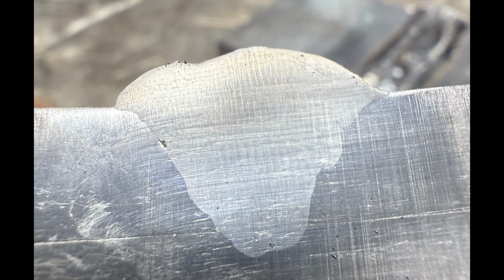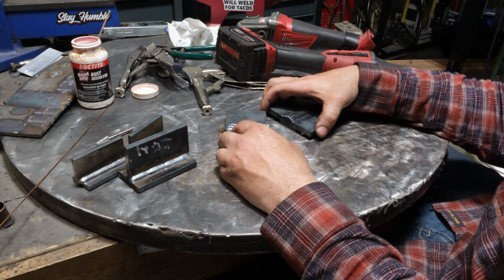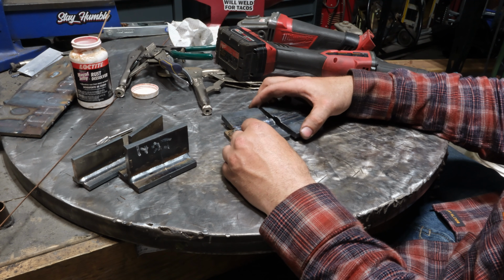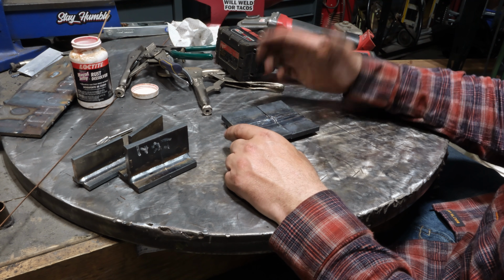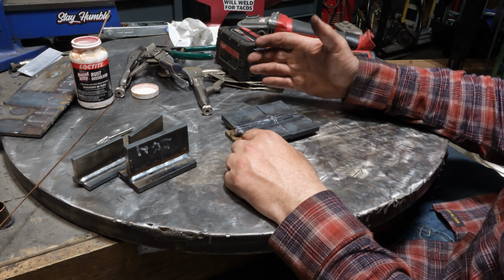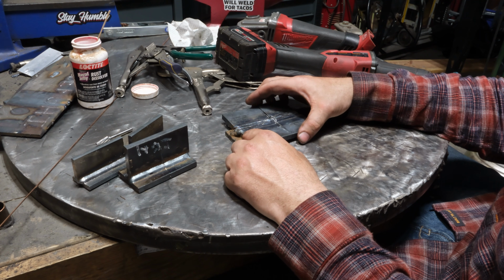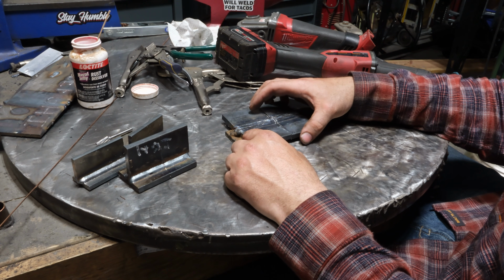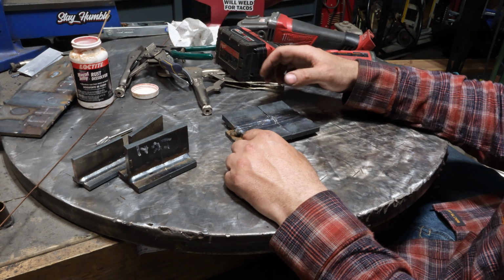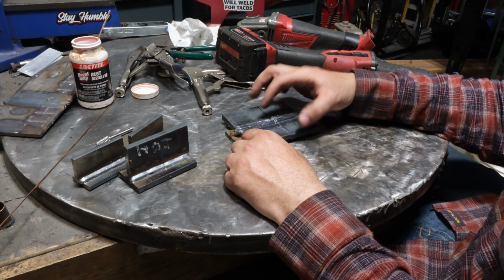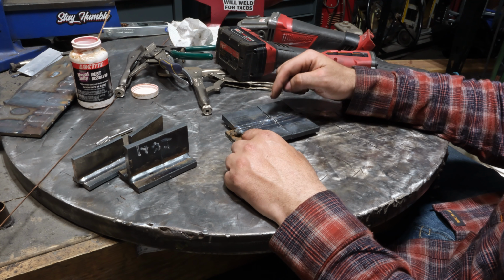I mean, this is probably 1/3 of the thickness of the weld that is suspect on this. That's definitely not good, because if the weld isn't fused in and attached to anything, you don't have any strength. So the structural weld here, the performance was a little bit lackluster. And unfortunately, with the short circuit process, it really has questionable sidewall fusion at times. Even spray arc can have questionable sidewall fusion. And based on what I see here, this is kind of what I expected.